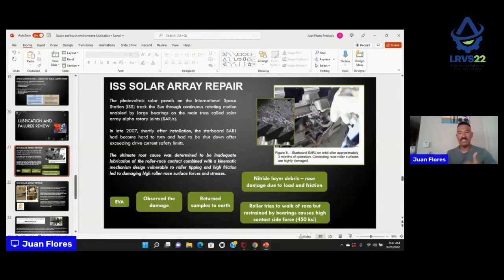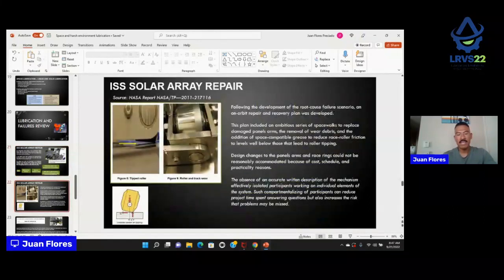The labs from NASA had to assess the damage, and they realized that the nitride layer on one of the surfaces showed significant damage, and they thought that it was exposed to a very high contact pressure. They basically simulated the same environment at NASA, and they realized that one of the rollers was slightly tipped and slightly tilted, and therefore, because the surface area was significantly lower, it was a very high contact pressure. Because it was a very high contact pressure, then the nitride layer wasn't able to withstand that damage. Basically, what they did is they sent an astronaut to repair the process, reapply a new coating to the rollers, and they had to use a highly stable vacuum grease to repair this mechanism. So it was a huge effort because of a bad tribology design.